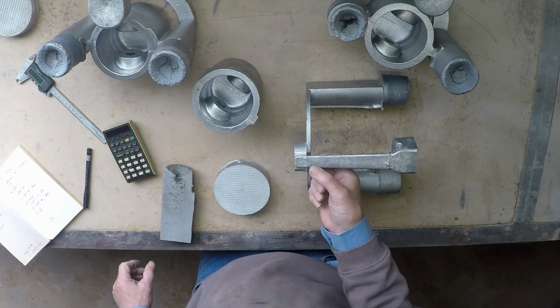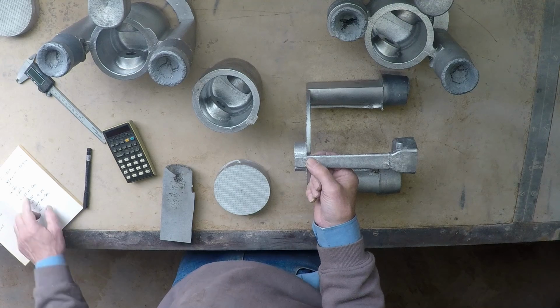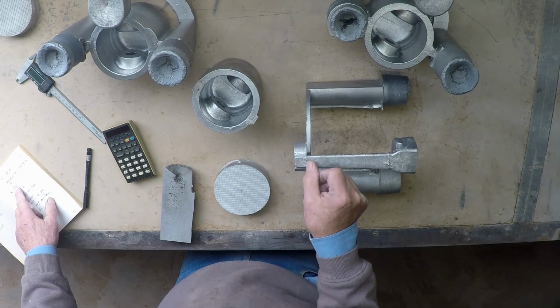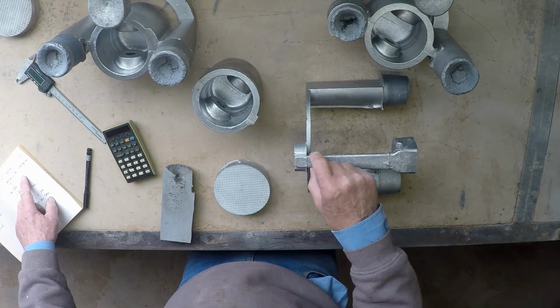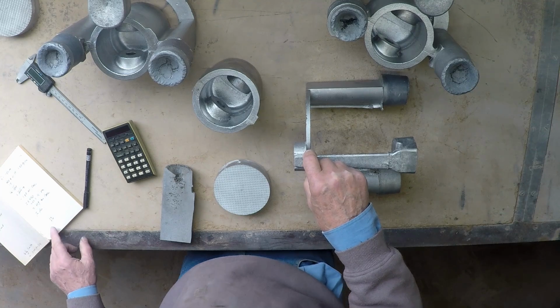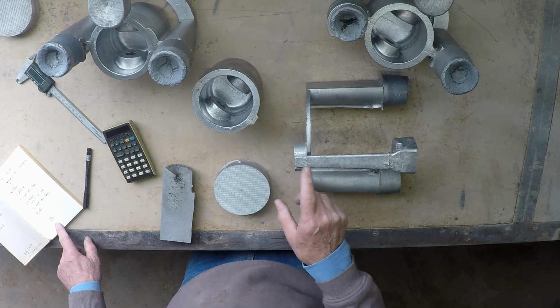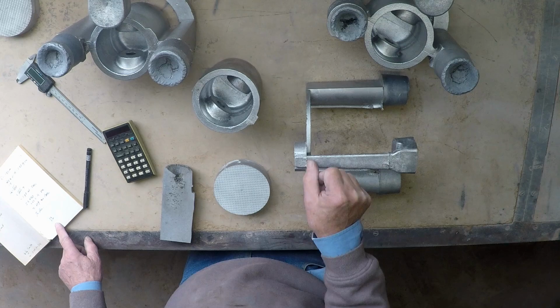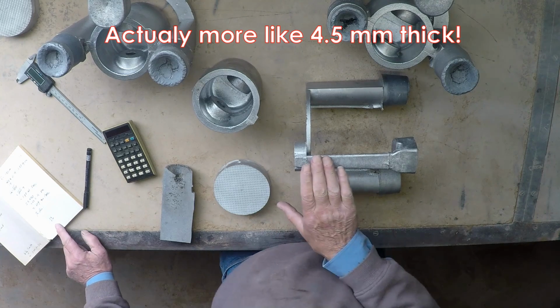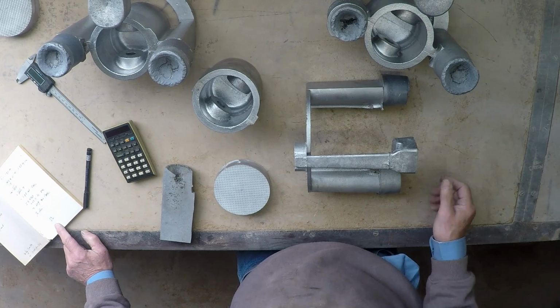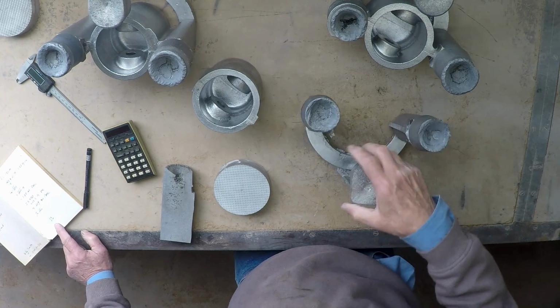So we will probably cut this sprue, which at the moment's just under 6 millimeter thick by nearly 22 wide. We'll probably cut that down to about 3.5 millimetre thick, and cut it down all over its length by that amount, by 1.5 millimetres, 2 millimetres, that sort of thing.